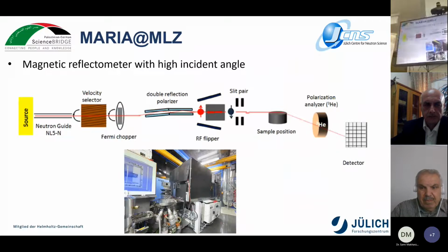The other instrument that I use, the neutron instrument, as I said, is MARIA, to measure polarized neutron reflectometry, and it's a magnetic reflectometer situated in the MLZ guide hall with a high incident angle. Here we can see a real image of this instrument, exactly the sample position, where we have a hexapod and also a cryostat situated around the sample in order to control the temperature. This instrument can measure polarized neutron reflectometry to obtain the out-of-plane structure. Also, we can perform grazing incidence small angle neutron scattering measurements in order to probe the magnetic lateral order of my system.